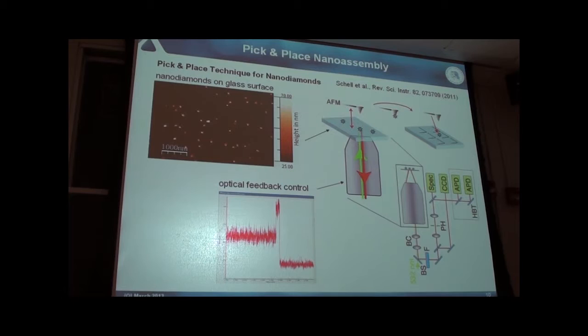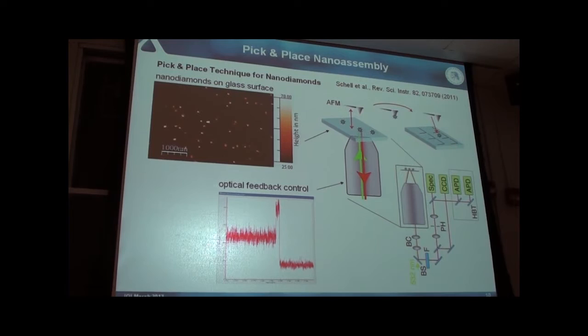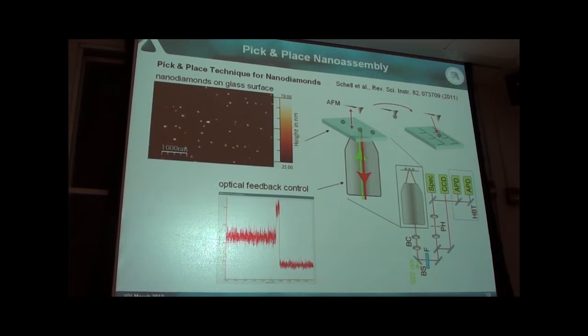Audience question: Are these nanodiamonds made from powder or ground? In this case, some come from explosion reactors — you put graphite in a reactor with TNT, explode it, and have high pressure. Then you have graphite around the diamond that you have to clean by etching off the graphite. In the end, you can buy it commercially. There's some size distribution, so you don't want an ultra-broad distribution. It's commercially available but not an ultra-clean material. It's not from grinding powder — it's more refined, cleaned samples, but commercially available.